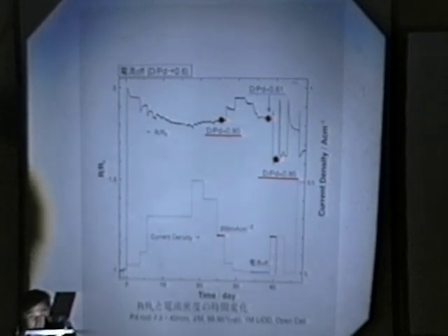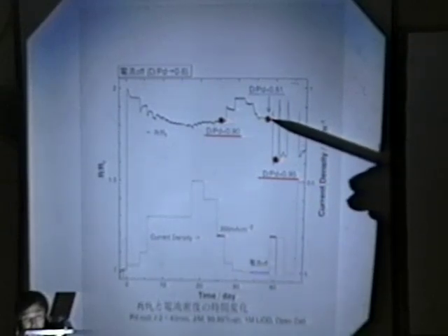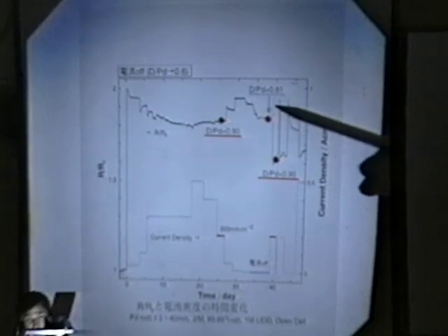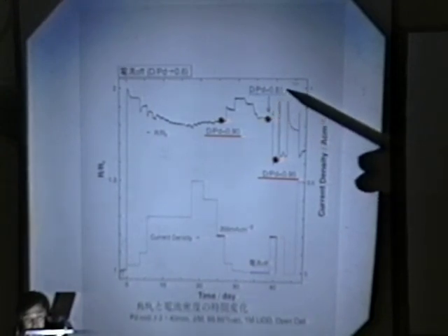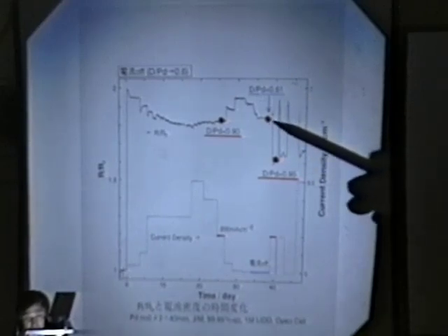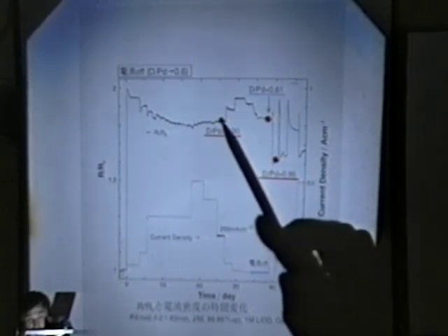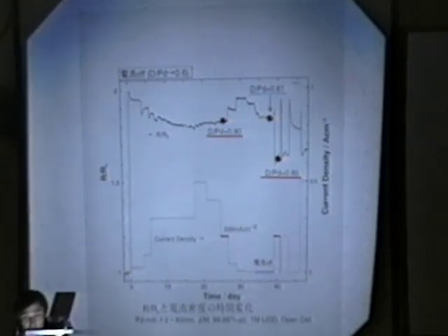And again, one more thing I would like to show is the effect of the load-deload cycle. I don't know what we are doing here, but we have found it is very interesting. If we load to 0.9 in 1 molar LiOD at 200 milliamperes, then switch off the electric current and wait for some time until we have deloaded the palladium, which shows 0.81 of D over Pd. Then at this stage, we switched on the electric current again at 200 milliamperes per square centimeter. We found that from this 0.90, the loading changed to 0.95. So we have a very large improvement of something like 5%.